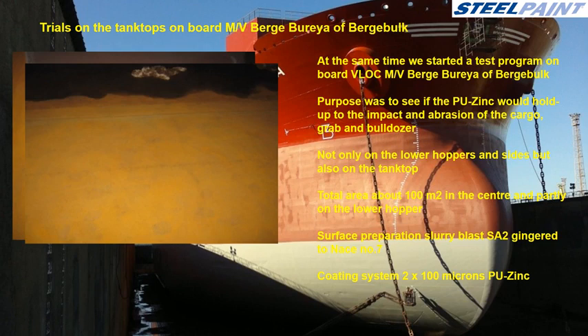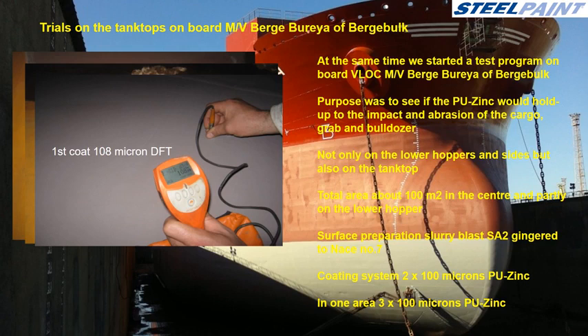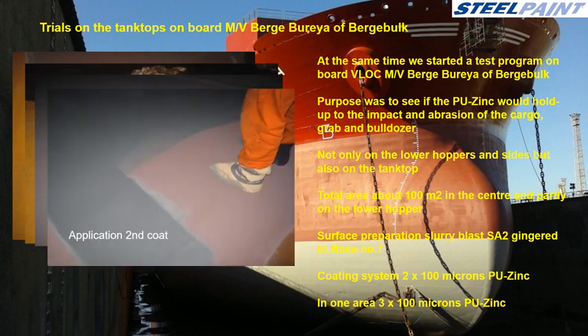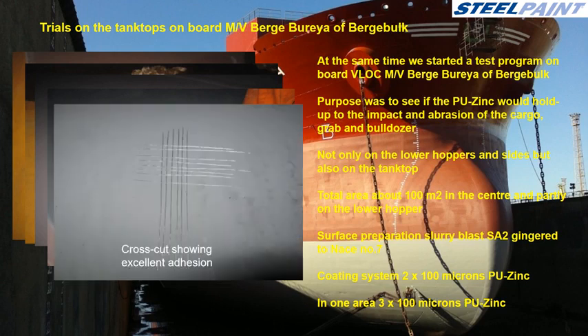Coating system: 2 times 100 microns PU zinc. In one area we tried 3 times 100 microns of zinc to see if there would be any difference. This is the first coat of PU zinc, reddish gray, at a film thickness of 108 microns. Application of the second coat, PU zinc gray. Here we see a cross-cut test showing excellent adhesion between the PU zinc and the substrate and itself.